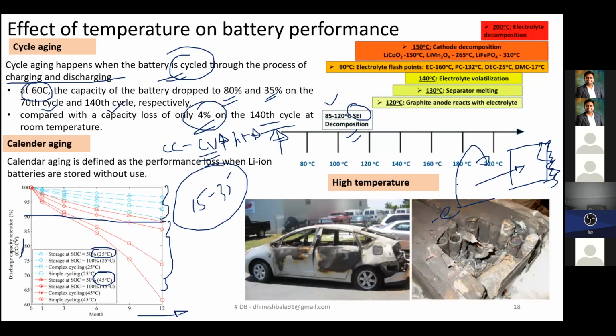So in all this thermal runaway condition or high temperature condition, in each and every high temperature part, you are just opening the pathway for the electron to move in the horizontal direction. And at 130, the separator would get melted. At 140, your electrolyte volatilization would happen, and at 150, the cathode decomposition would happen.